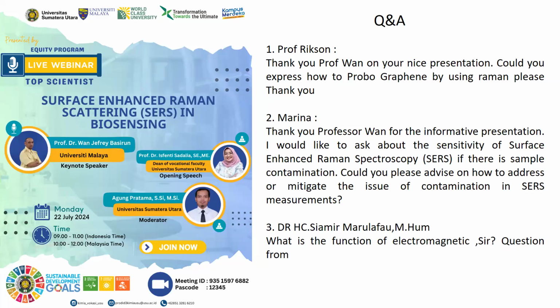Graphene oxide is a single layer of graphene, but it has carboxylic groups, carbonyl groups, and carbon OH groups. It has many functional groups, because when you oxidize graphite, you get graphene oxide. The surface of the graphene layer is covered by carboxylic, carbonyl and OH groups, so that surface now becomes disordered. So when you run the Raman spectrum, the ID over IG will be much larger compared to pure graphite. That is how you analyze graphene material in Raman spectrum.